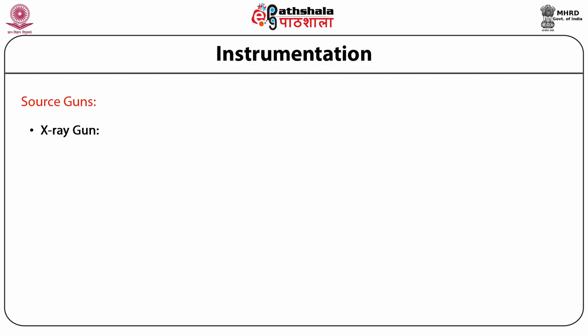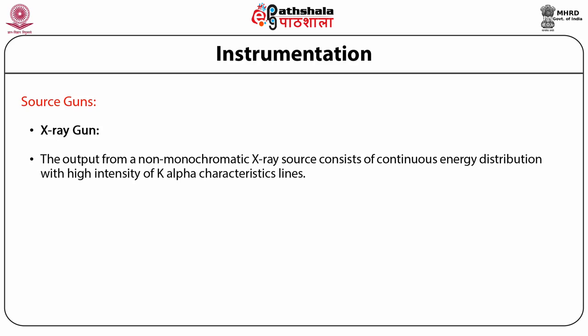First, the X-ray gun. An electron spectrometer system contains an X-ray gun for XPS analysis. The X-ray gun produces a characteristic X-ray line to excite atoms of the surface to be analyzed. The XPS uses monochromatic and non-monochromatic X-ray sources. The output from a non-monochromatic X-ray source consists of continuous energy distribution with high intensity of K alpha characteristic lines. The monochromatic source produces output by removing continuous X-rays from the irradiation spectrum.